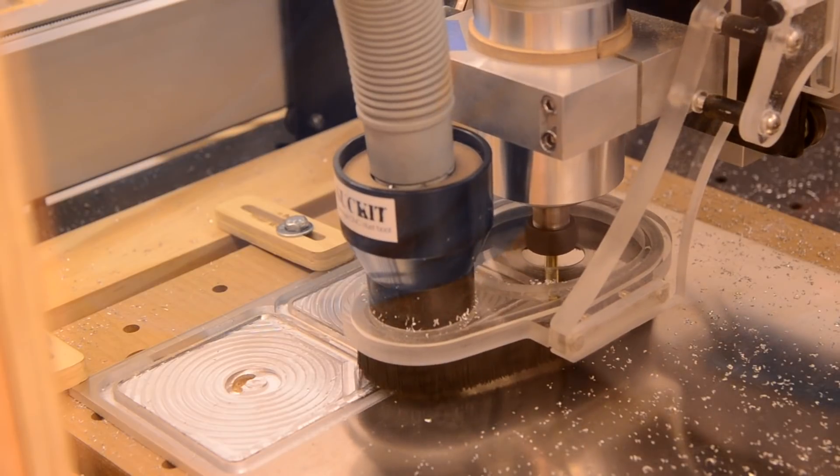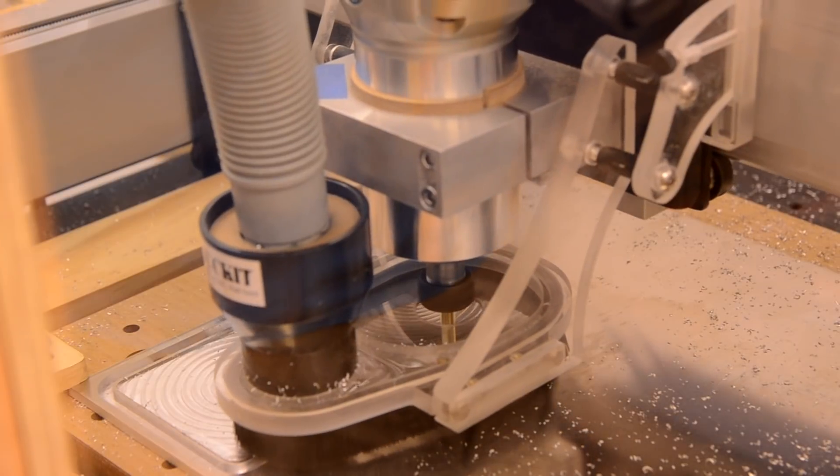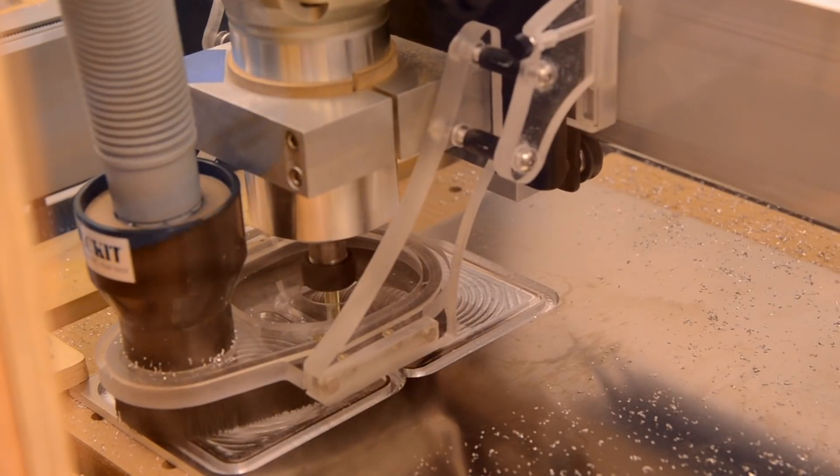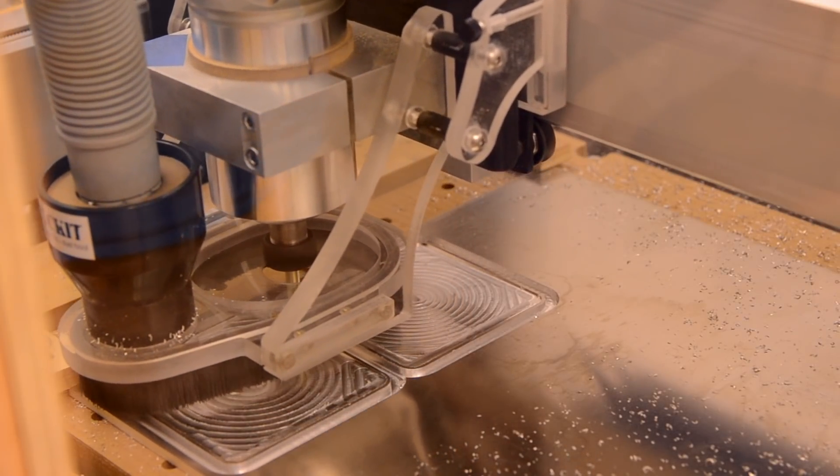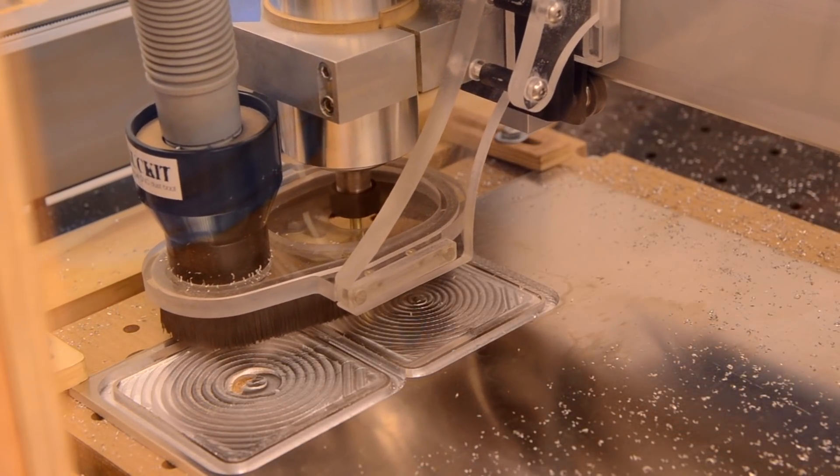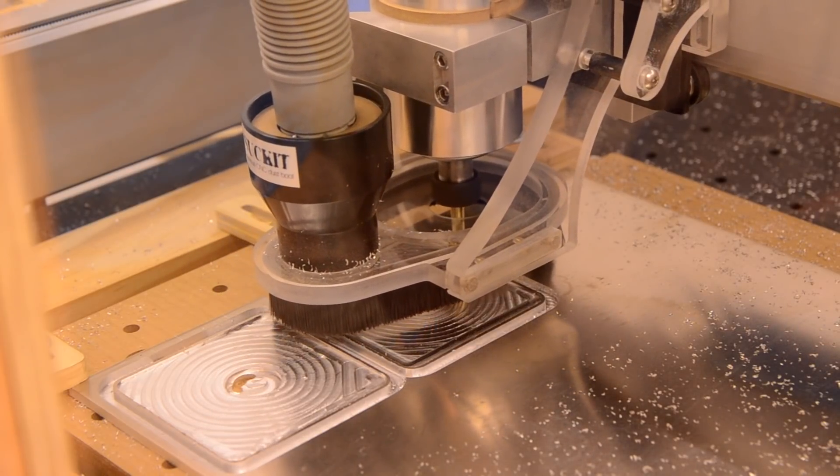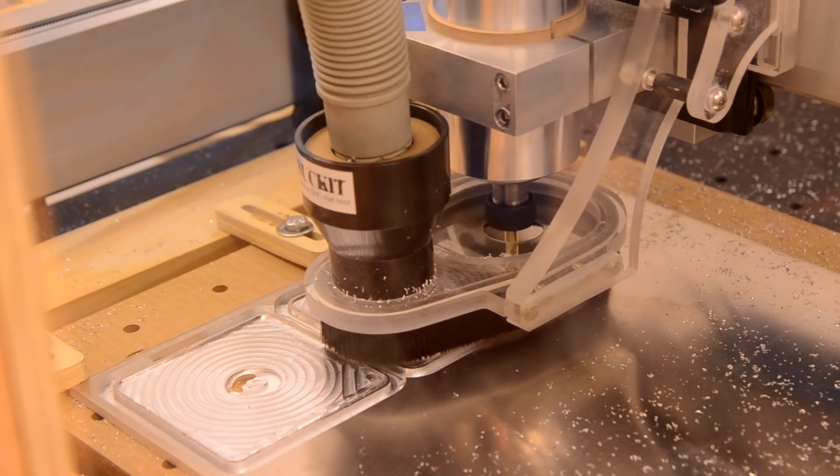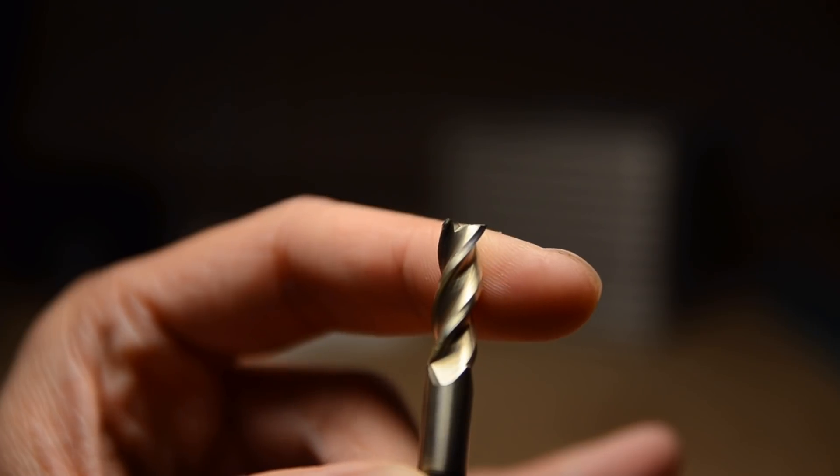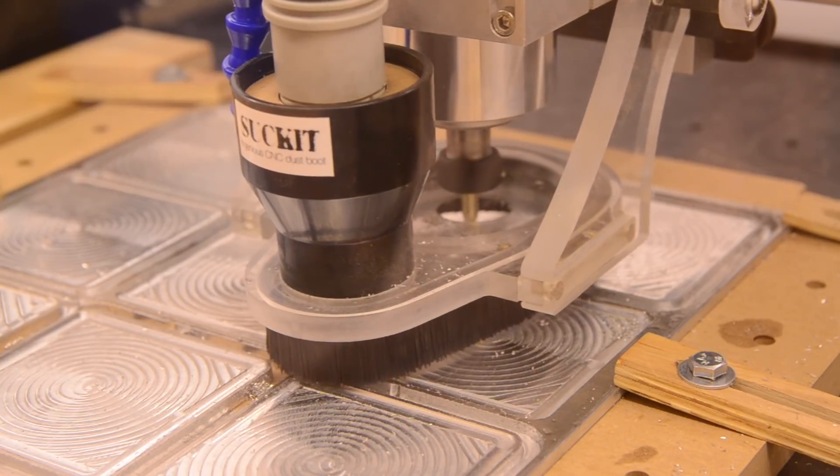Contour cutting in metals is probably the single most stressful thing you can do on a Shapeoko. Without the benefit of a steady stream of cutting fluid, tool engagement on both sides of the machine slot causes a substantial amount of friction. This manifests itself as heat, which is generally terrible for cutter life. This is the crux of machining aluminum with hobby grade machines. They might be powerful enough to cut metal, but thermal considerations and limited rigidity restrict what you can do. In the triangle of engineering trade-offs between good, cheap, and fast, the latter leg is what you're going to be missing out here. Despite destroying the coating on my cutter, I tried pressing on until I received the final nail in the coffin for machining the coaster blanks on my Shapeoko.